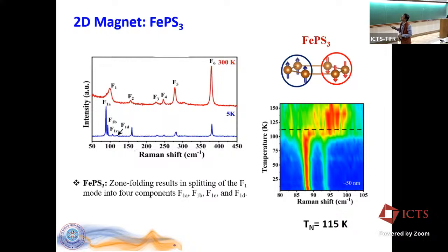Here what happens is, the F1 mode, the lowest frequency mode in this spectrum, splits into 4 components. Why does it happen? There's something called zone folding. If you look at the crystal structure, you have a certain ordering of the atoms, but now when the magnets are turned on, you have a different magnetic lattice. So the 2 structures are different, and now if you work out the zone boundary, the Brillouin zones of the magnetic structure and the crystal structure, you will find that the 2 fold with each other. So the zone folding basically gives rise to 4 modes at the zone center, okay? Which is the signature of this magnetic transition in FePS3, from 1 component to 4 different components.